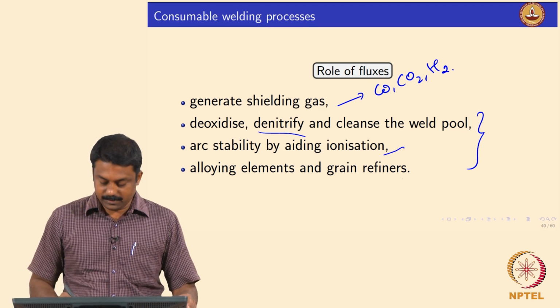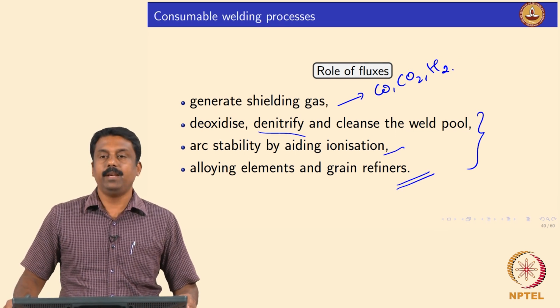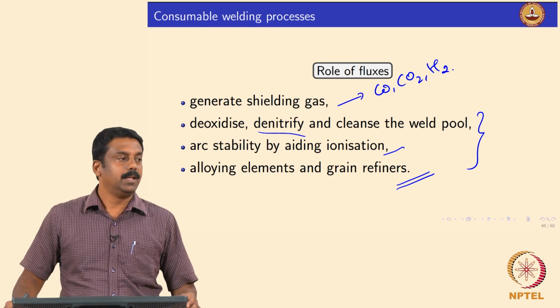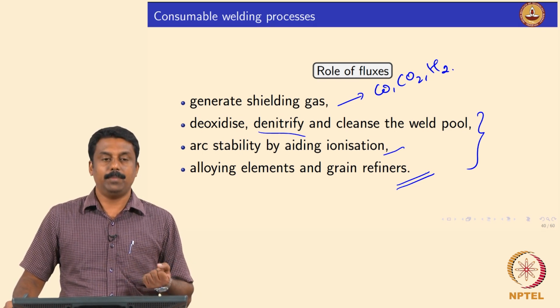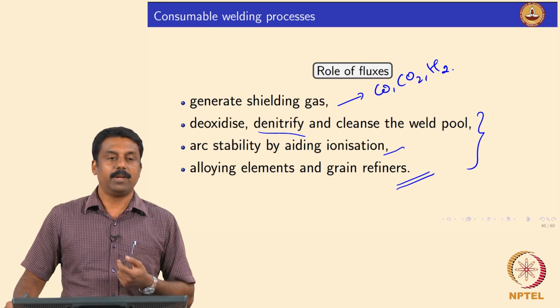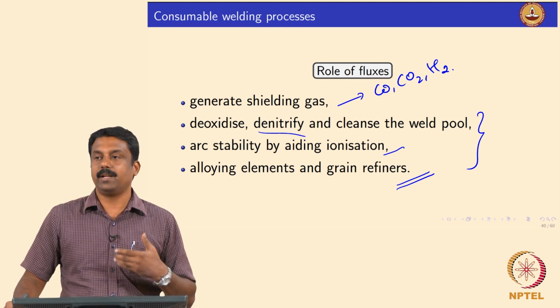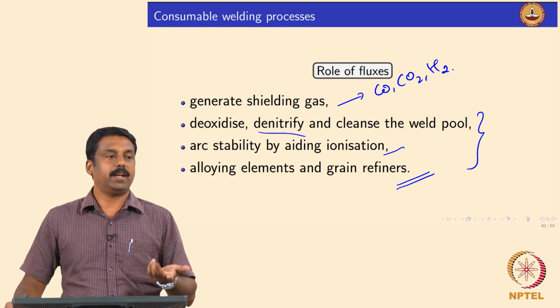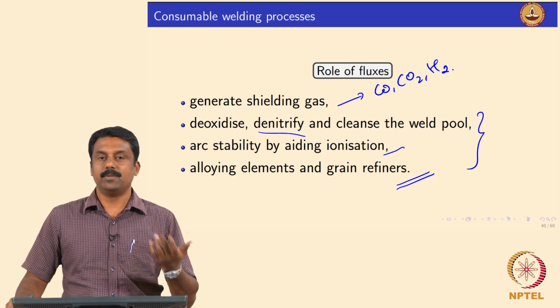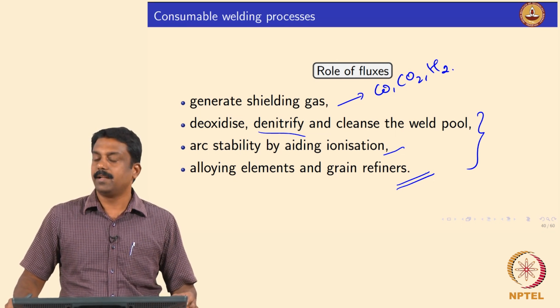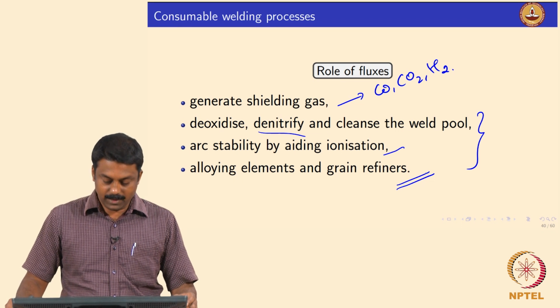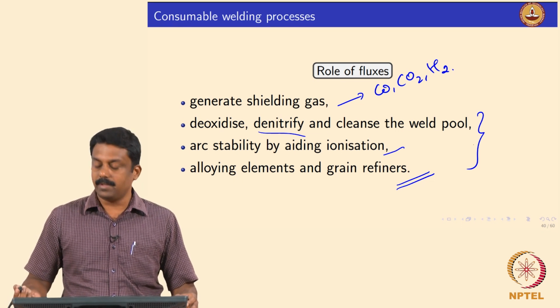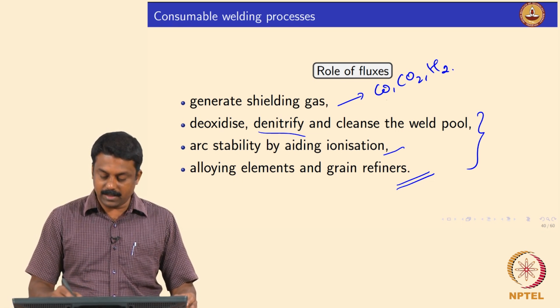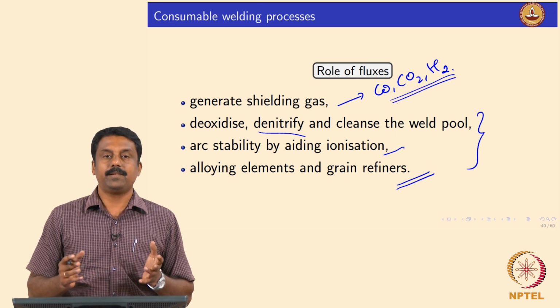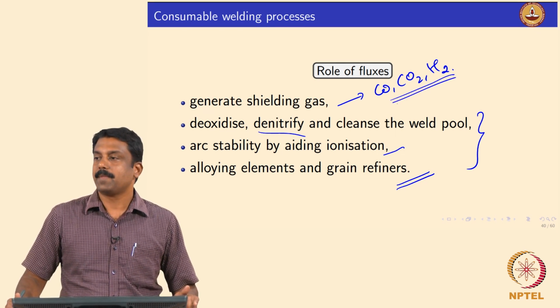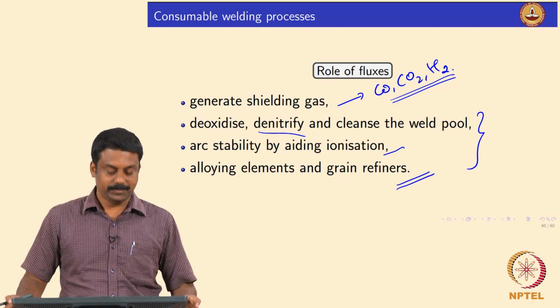Of course, these fluxes can also be added to change the alloy composition of the weld metal. So, you can also add precipitation inducing elements like ferro-niobium, ferro-titanium in steels, and you can also add grain refining elements in the fluxes. So, these are all the secondary functions, but the primary function in these processes is to generate shielding gas, right. Good.